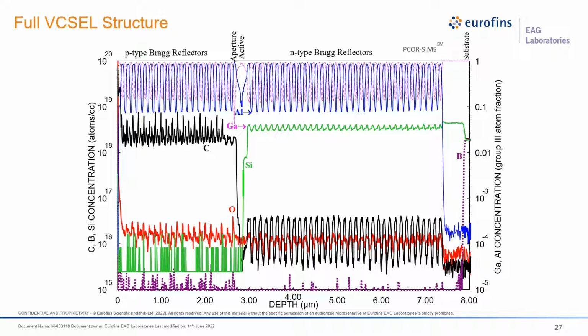To provide current and optical confinement, producers of VCSELs tend to introduce a high aluminum content aperture, which we can see in this slide here. And the aperture is oxidized from the outside inward. Halting the process at an appropriate point leaves an unoxidized aperture through which the current and light can pass. Obviously, to have a repeatable oxidation process, the rate of oxidation must not vary. This implies that there must be stringent composition control and uniformity of the aluminum gallium arsenide layer because the oxidation rates vary by more than 2 orders of magnitude when the aluminum content is increased from aluminum 0.82 to aluminum 1.0.